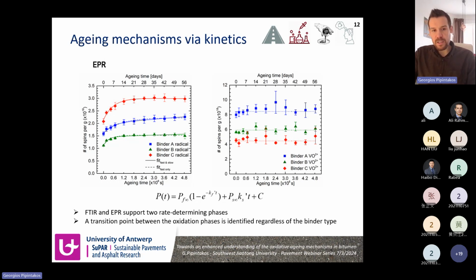What this shows us is that the rate of production and the rate of consumption of the carbon center radicals, around 8 days, become equal. For that reason, we don't observe either an increase or decrease of these carbon center radicals. Moreover, the hypothesis of the aging mechanism claimed that we can have oxygen center radicals. However, the oxygen center radicals are rather too short-lived, so they are not able to be captured with such a technique.